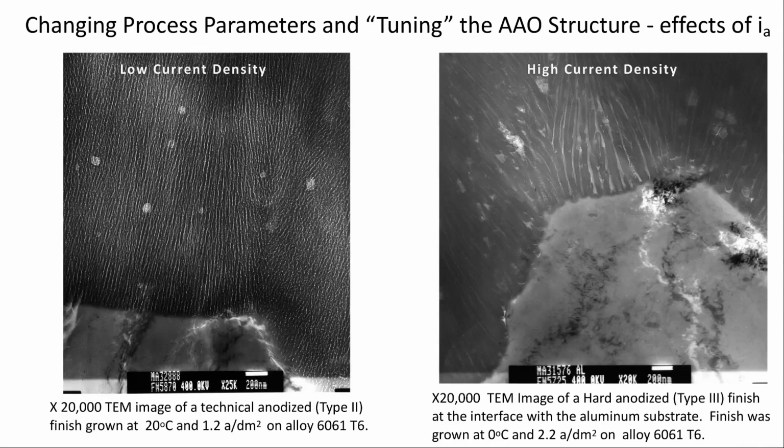We see the effect of pockets of empty space due to deformation in the alloy. And we see here the adjacent bases of oxide columns that have let go while the applied current is pushing the electrons through, and we have this incidental pocket of no aluminum. So the structure lets go intermittently till it grows around it, and then order is restored.